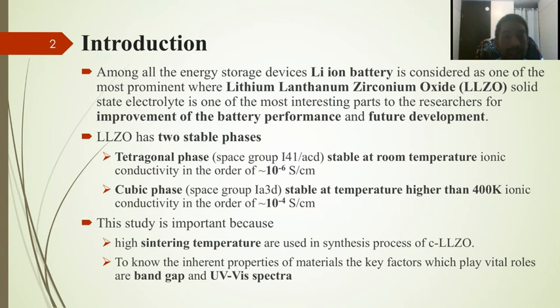LLZO has two stable phases. The tetragonal phase is stable at room temperature and has very low ionic conductivity, on the order of 10 to the power minus 6 Siemens per centimeter. The other is the cubic phase, which is stable at higher temperature, generally more than 400 Kelvin, and has a somewhat higher ionic conductivity, as you can see. Why is this study important? Because the synthesis process for LLZO is sintered at higher temperature, generally 1230 centigrade, so almost 1500 Kelvin. This study will show the band gap and UV spectra analysis, because this is an inherent property of materials.